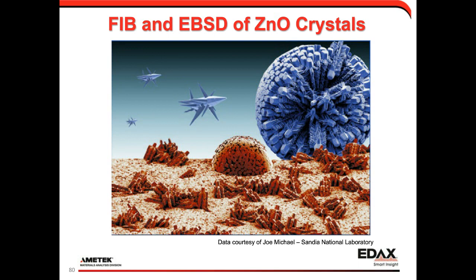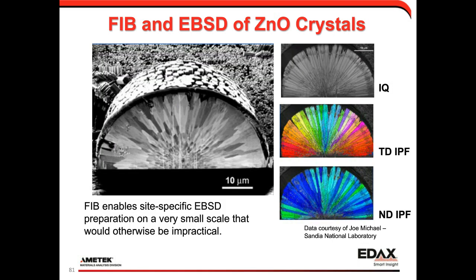And these are some very cool crystals, courtesy of Joe Michael at Sandia National Laboratory. These are zinc oxide crystals, which form these balls that kind of look like a porcupine ball. And Joe has come in here and sectioned across that, and then you can see the cross section where we see the crystals growing radially from that structure, and we can see the orientations growing in different sample reference directions using the EBSD results.